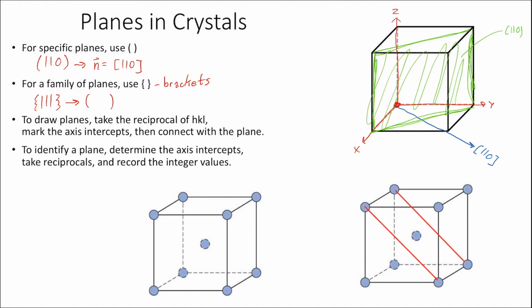All right, so starting with the 1, 1, 1, we're just going to write down the same plane for this. Now, what we can do is permute where the negative sign is. We can put the negative sign on the first one, on the second one, and then on the last one. And now maybe during that 30-second break, you wrote out some other planes. The other possibilities are just making the negative of all these planes.